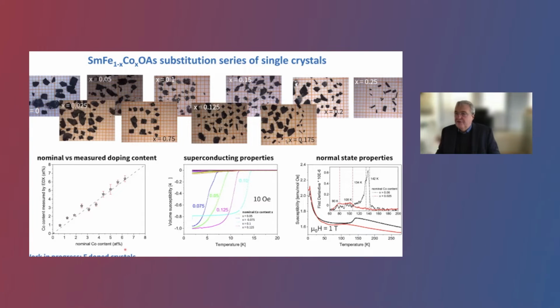That's not the end of the story, I should emphasize. So we are still working on that. We are still working on improving the single crystals. So the next step is a series of samarium 1111 type compounds, where we again started the cobalt doping. There's an entire series of samples that exist. We have now better superconducting properties here, because samarium, also in the fluorine-doped compounds, leads to higher TC. And this is work in progress. And I will tell more on that in the next years, hopefully. And in addition, we also have first steps towards fluorine-doped crystals. Okay, that's work in progress.